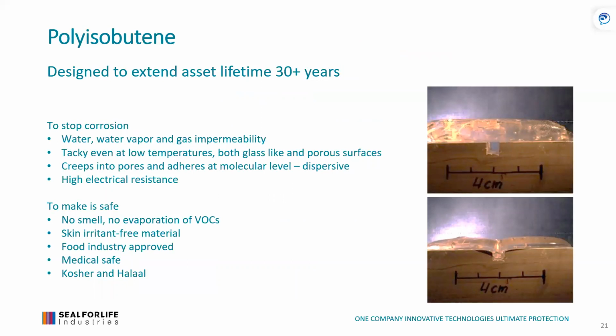So how did we do it? Our approach back then was to select as many polymers as possible that are available in the market, with a track record, primarily what stops corrosion. Eliminate oxygen, and you eliminate oxidation really. So select a polymer that doesn't allow oxygen and water to go through it, to have immediate adhesion of a dispersive kind, so without a roughness, etc., something that never cures, because a coating that never cures will always have that adhesion and the flow, etc. The same reason why we don't apply dry paint, we apply wet paint.